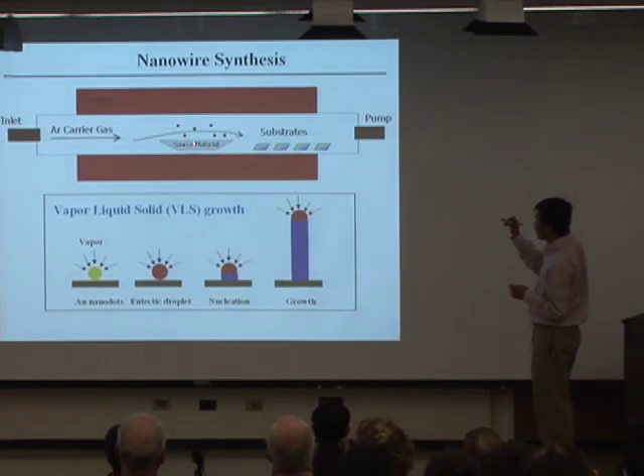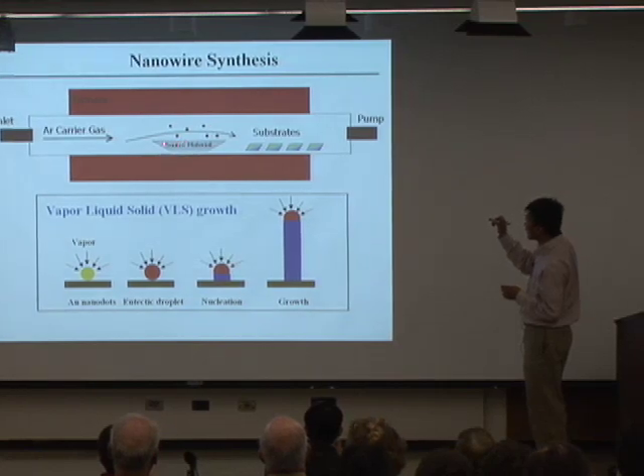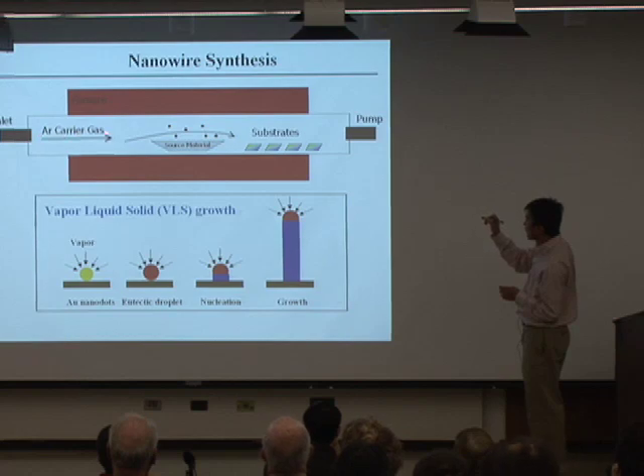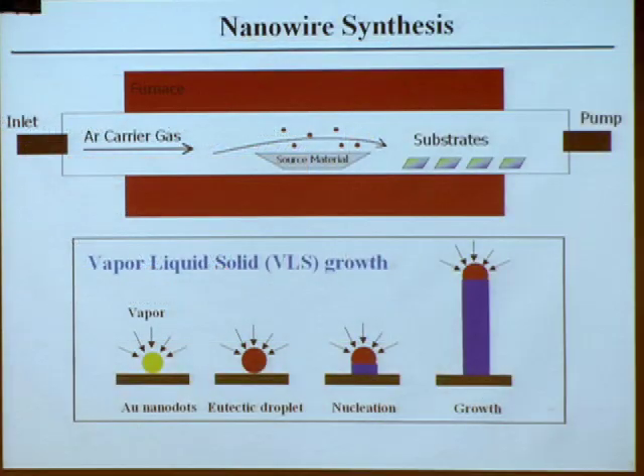But let me mention how we made these nanomaterials. Mention it a little bit so you have some background. The way we made these materials, this is the material we would like to make into nanowire. We heat up the furnace and vaporize this material, carry gas coming down, and take it to the downstream. This is a little bit lower temperature with this nanoparticle catalyst, metallic catalyst on the surface. This nanoscale catalyst functions as a really good solvent above a certain temperature to dissolve these materials from vapor phase going into liquid phase. After supersaturation, they nucleate and grow into this one-dimensional nanowire structure.